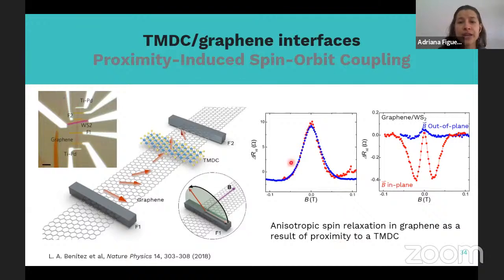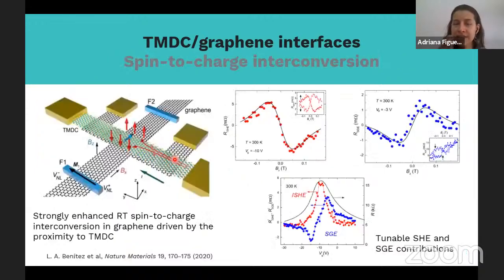So you study the spin transport in two different geometries, and you see that it is characterized as anisotropic. That is a result of the spin-orbit coupling that is being imprinted into the graphene because of proximity with the TMD. Another consequence is that you have spin-to-charge conversion at these interfaces, even up to room temperature, driven by that proximity to the TMD.